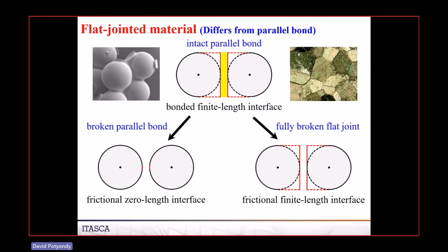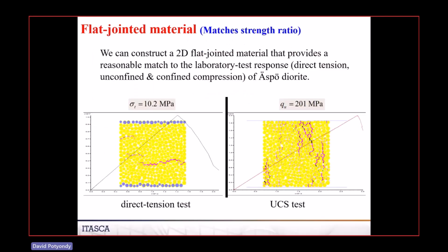Therefore, by choosing the micro shear strength, you can dial up the UCS to these relatively large numbers. And so that's why the flat jointed material can give you these high values of UCS relative to tensile strength. That's also why these Voronoi block materials can do the same thing, because the material during a UCS test is able to keep on taking lots of damage before it finally will fail. All right. So that's a solution to this problem of the UCS being too small relative to the tensile strength.